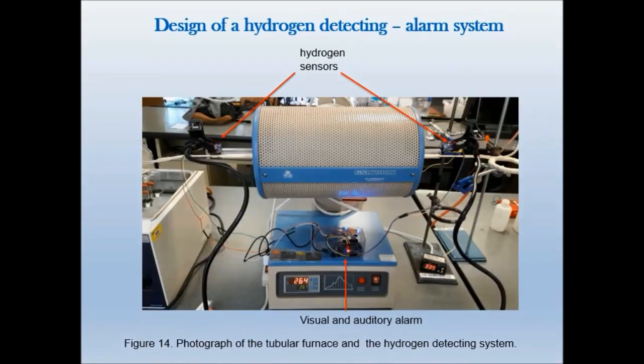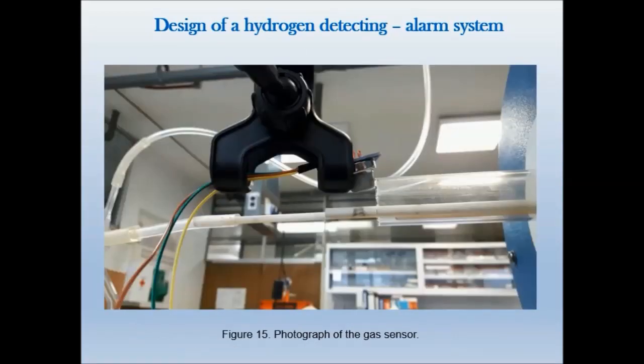Here's a picture of the tubular furnace together with our hydrogen detecting system. The two hydrogen sensors are placed close to the ends of the furnace, and at the center is the visual and auditory alarm. Zooming into the area where the hydrogen sensors are is where this picture comes from. Here we can see the quartz tube protruding out of the furnace and the sensor very close to it.